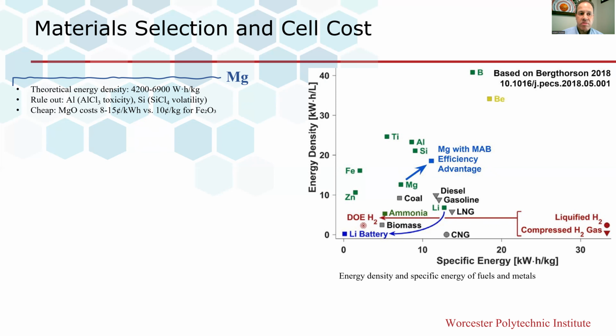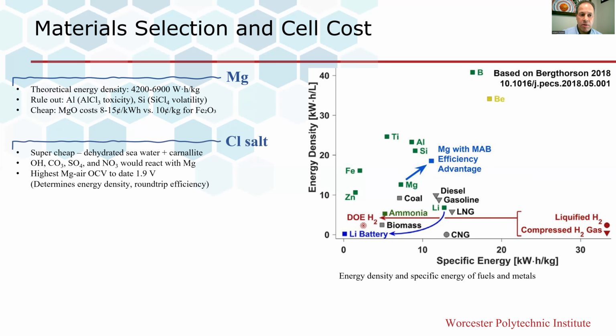It is very cheap also, that the magnesium oxide, which would be the feedstock for this, costs just 8 to 15 cents per kilowatt hour of battery storage. That compares favorably with about 10 cents for the hematite ore of iron oxide used in an iron air battery. The chloride salt is basically dehydrated seawater plus carnallite, so it avoids all of the complex ions that would react with magnesium. And in this molten salt, we have achieved 1.9 volt open circuit voltage, which is the highest magnesium air open circuit voltage to date for any magnesium air chemistry battery.